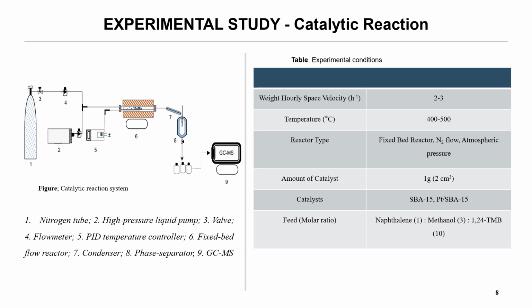Subsequently, the reactions were then carried out at temperatures of 400 to 500 degrees Celsius and with weight hourly space velocity of 2 to 3 per hour. The reaction products were condensed and analyzed in a gas chromatograph connected to a mass spectrometer.